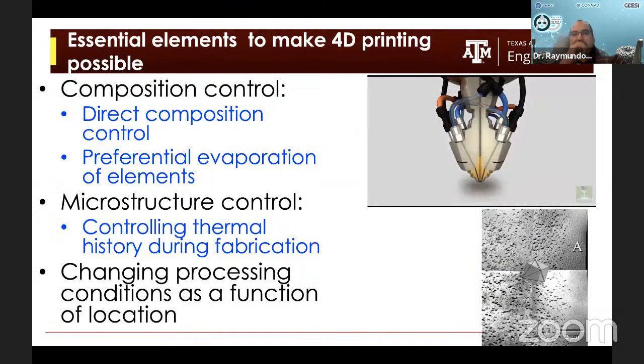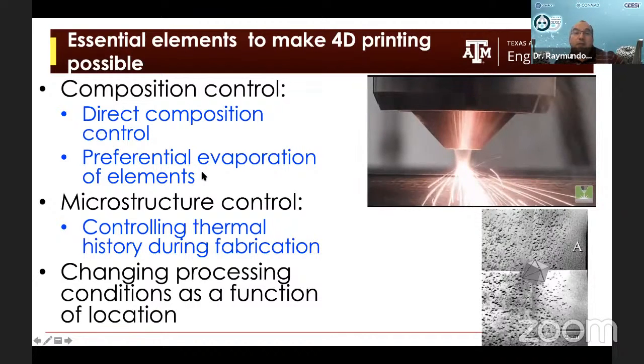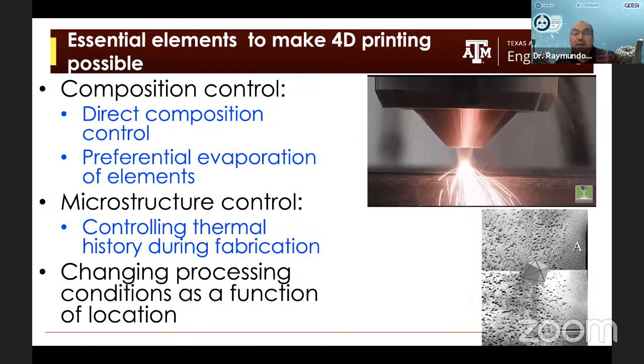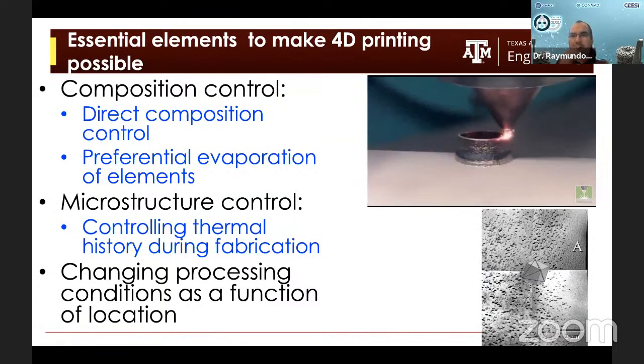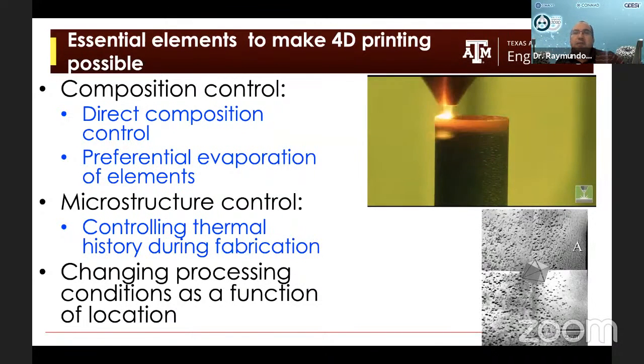So the essential elements to make 4D printing possible are composition control. So we could potentially use DED to deposit alloys with slightly different compositions, or we can exploit the fact that different elements actually have different vapor pressures. And you probably are familiar with this problem in additive manufacturing. The final composition doesn't match the initial composition of the alloys, because if the elements have a very large difference in the vapor pressure, you are going to evaporate some elements more than others, and that changes the chemical makeup of the part.